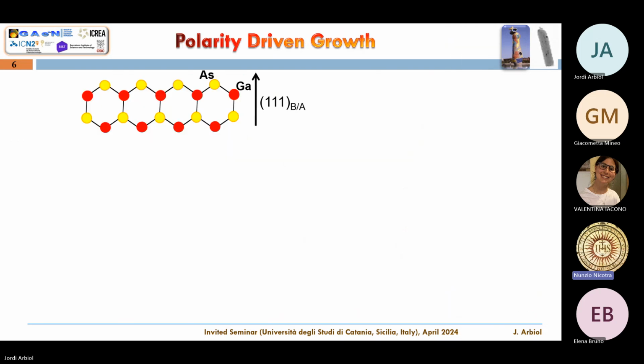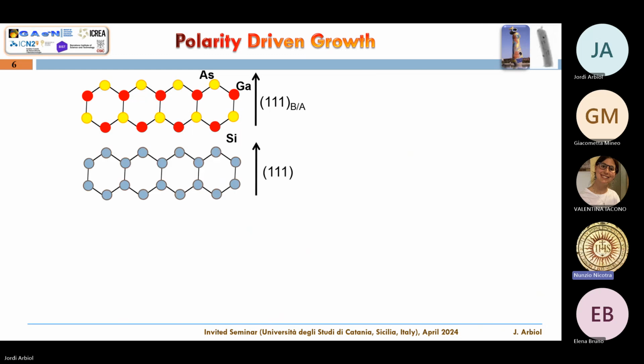But following these simple rules, that in every fast growth condition what you get is always the anion on top, you can realize that if you want to grow on top of nonpolar materials like silicon or germanium, all the atoms are silicon, so there's no polarity. So that means that the first seed that you are nucleating on top of the substrate can be terminated in either the cation or the anion, it doesn't matter. So at the end, you just nucleate, and depending on the growth conditions, you will get one or the other.